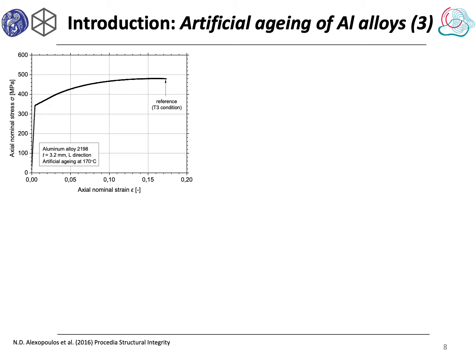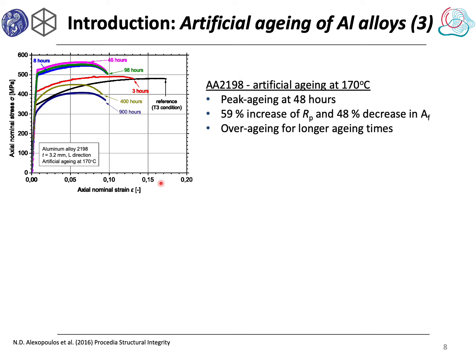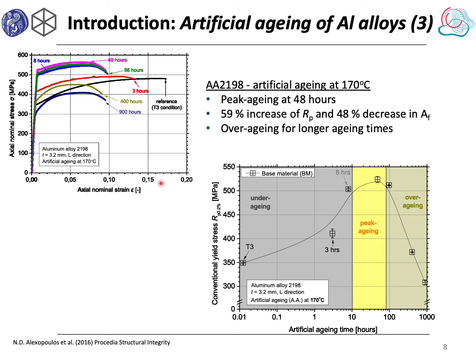The tensile mechanical behavior of various artificial aging times was examined in the literature. Here we can see stress-strain curves with increasing aging times up to 900 hours. More analytically, yield stress continuously increases with aging time up to 8 hours. This increase in yield stress is characterized as the under-aged region.